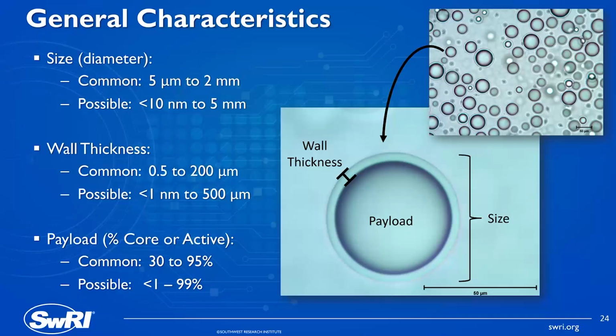Hey, somebody's done this, but have they done it at scale? So the common is more at scale, and there's going to be a few exceptions to this. But in general, if I were to go to a spray drying company, 5-10 microns is most likely the bottom end of where they're going to be. Up to prilling and maybe even fluid bed or some of the vibratory nozzle systems, that's where you can get the millimeters. So, but possible, certainly less than tens of nanometers, especially with molecular complexation. And then 5 millimeters is kind of a random top end. You can certainly go higher, but you start to get into macro encapsulation technology.